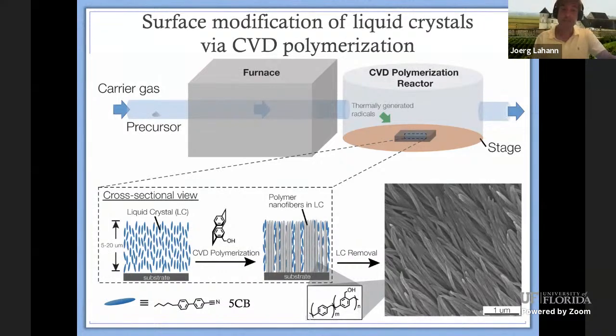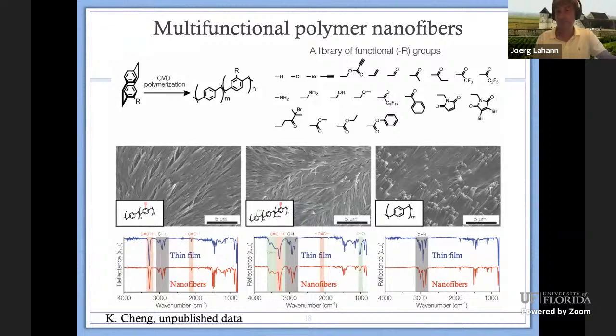That was interesting because now we have essentially this ability to topologically control surfaces as well. So instead of getting only thin films that are conformally coating the surface, we can now essentially also create these well-defined arrays of nanofibers. And so here you see a few different polymers that we use. Again, this alkyne, we like that a lot because we can modify it easily. Copolymers, I didn't talk much about this, but we can make copolymers with this too by just combining paracyclophanes and then the base polymer here.